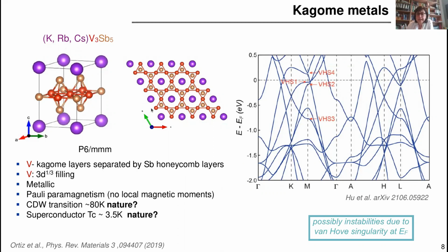If we count the electrons, we have 1 electron per 3 vanadiums. The system is metallic, and it shows Pauli paramagnetism, so there are no appreciable local magnetic moments. Now what's interesting is that by lowering the temperature, and this happens with all these different cations, the system undergoes a charge density wave transition at about 80 Kelvin.